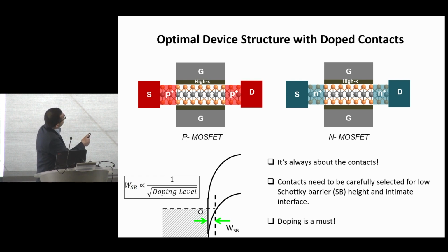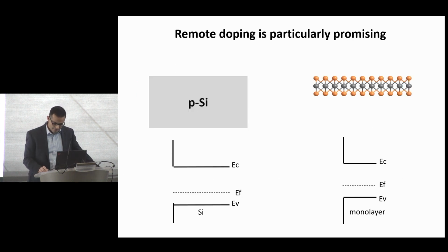The heavier the doping concentration, the thinner the barrier heights, the thinner the Schottky barriers at the interface, and the more tunneling, the higher the tunneling probability. So the key is to dope these ends, but dope them very, very heavily. Now, you can think about how to dope, and there are different doping schemes. You can do substitutional doping, for example, which was highlighted earlier today. But I think the most promising approach for doping 2D materials is remote doping.